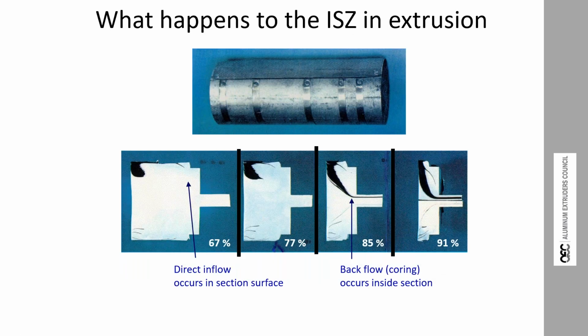Here's a little experiment. This was done by Hydro back in the 90s. They took a billet and machined off a little bit, and they replaced the inverse segregation zone with thin foils of alloy of unknown chemistry. The reason for this was the chemistry chosen. It had the same flow stress as the other aluminum at temperature, but when it was anodized, it came out jet black. So when we cut a billet up, we could anodize it and we can see the blackness.